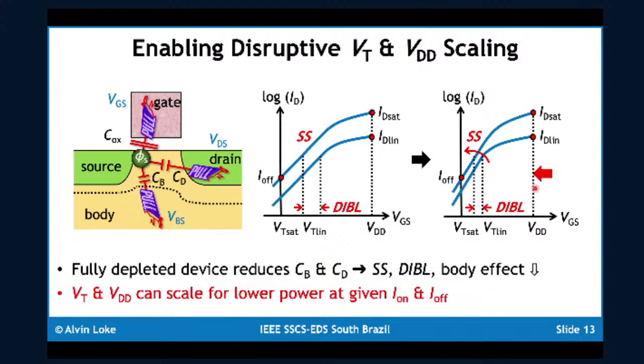If you hypothetically need 3 orders of magnitude separation, or 1000x difference between on and off current, that requires a minimum threshold voltage of 3 decades times 120 millivolts per decade, or a threshold voltage minimum of 360 millivolts. If you can bring this down to a much lower subthreshold swing, such as in a FinFET, the first FinFET nodes brought the subthreshold swing as low as 65 millivolts per decade.